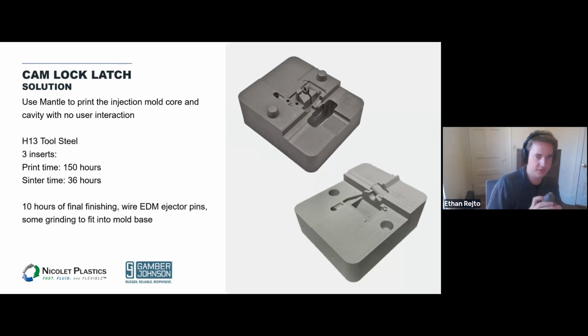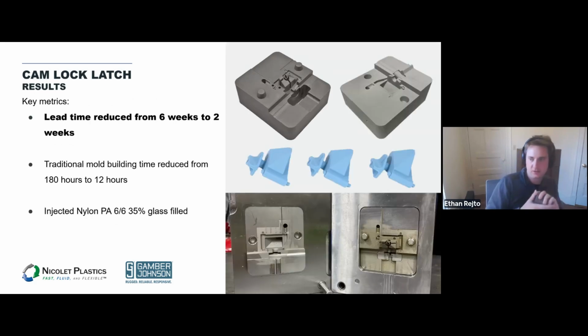They wire EDM the ejector pins. They did just a little bit of grinding to ensure the inserts fit well into the mold base and there wasn't any unnecessary flash or misalignment. You can see that the tool is actually in the mold here, and ultimately that enabled a lead time reduction from 6 weeks down to just 2 weeks.